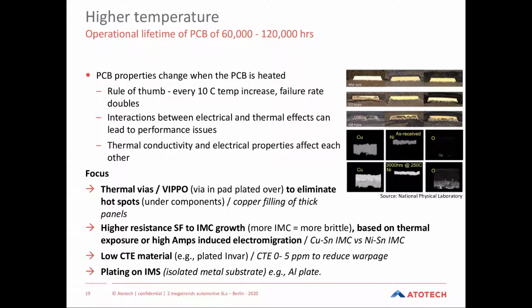Another effect is IMC formation by long-time thermal exposure or current-induced electromigration within solder joints, which is also well understood. This will impact reliability, as both high temperature and current-induced electromigration within solder joints will create more intermetallic compounds, and this will make the solder joints more brittle. So choices for surface finishes will be narrowed down to anything with nickel underneath, between the copper and the solder alloy. So either again a high phosphor nickel gold or a nickel palladium gold. Both show higher resistance towards intermetallic compound growth than typical surface finishes where copper tin IMCs are formed, as for example with OSP.